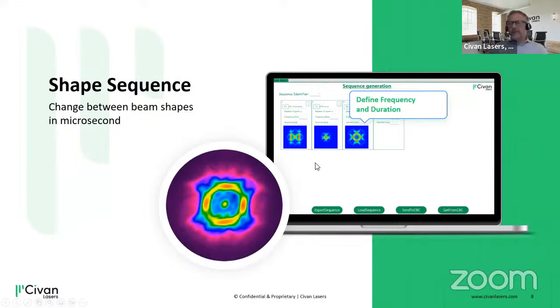Just an example, if you weld with 30 meters per minute or 500 millimeters per second, then you have about 1 millisecond at a particular place at the weld. So within this 1 millisecond, we can apply several beam shapes and address all the issues. And we do that without moving parts, because if we would come to moving parts, then the frequencies that are typically applied today for moving the beam are in the low kilohertz range. So we compare the low kilohertz range of moving an entire beam to the megahertz range of moving energy distribution inside the beam.